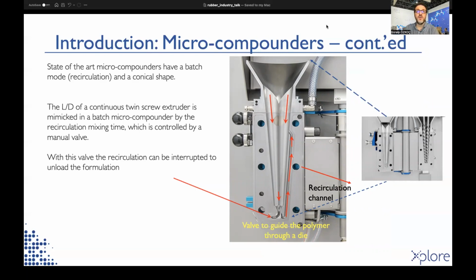State-of-the-art microcompounders have a batch mode, which is so-called recirculation, and a conical shape. How does this recirculation channel work? When we feed the polymer, it can be in granular form or in powder form. It's taken down by the screws into the barrel. There it melts with the help of the heated barrel and the friction of the screws. Then the melt is sheared and pressurized through the down part of the microcompounder.